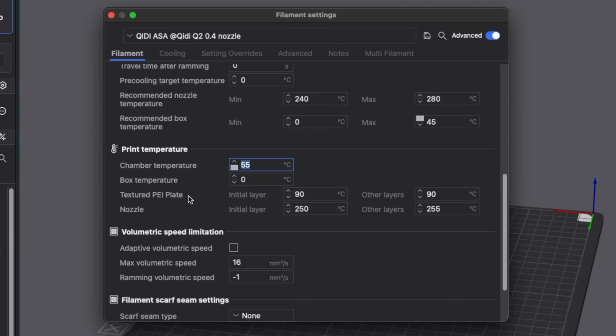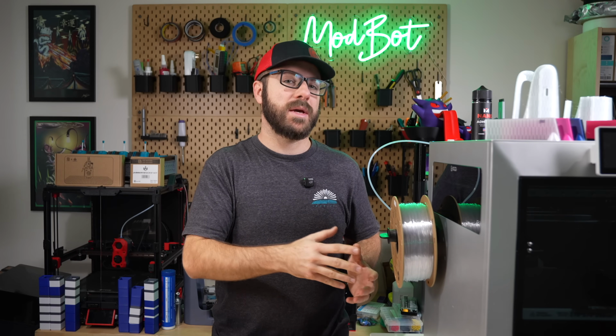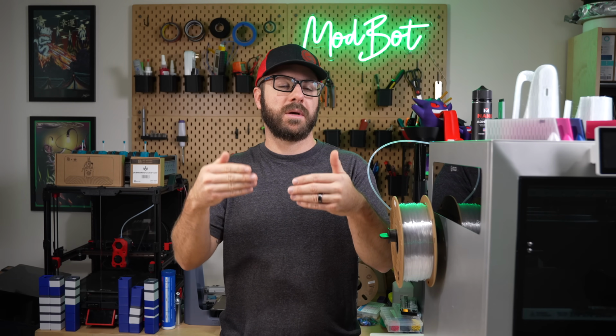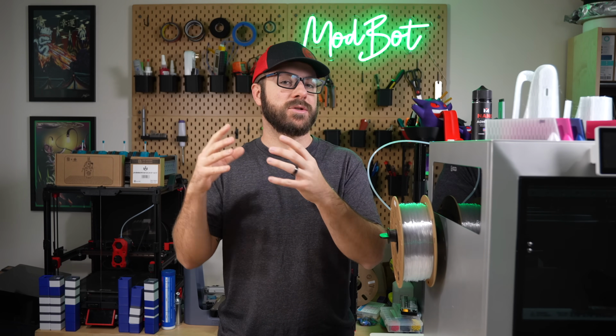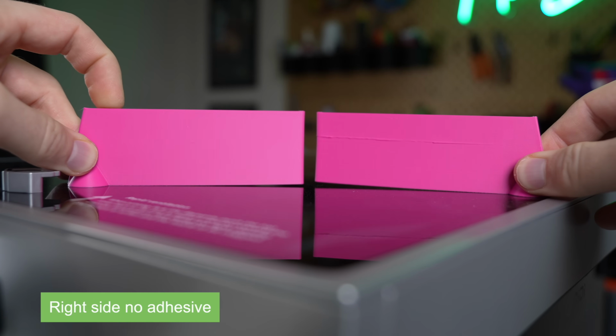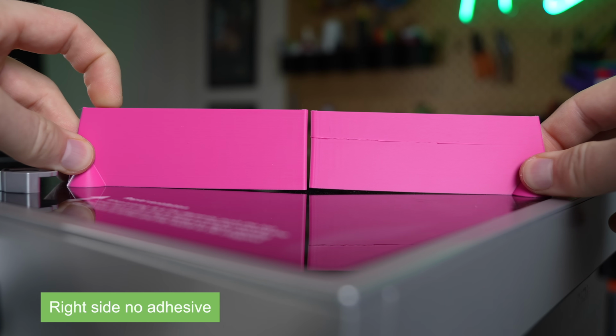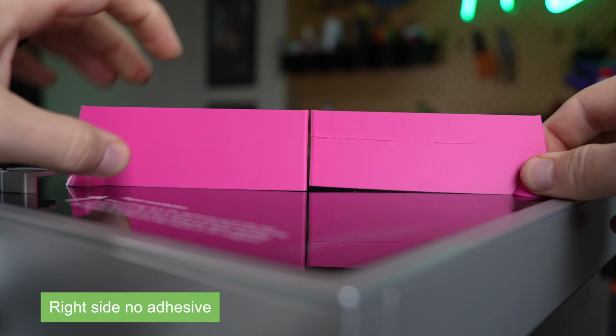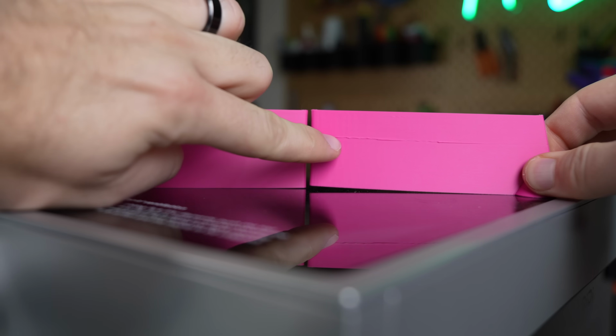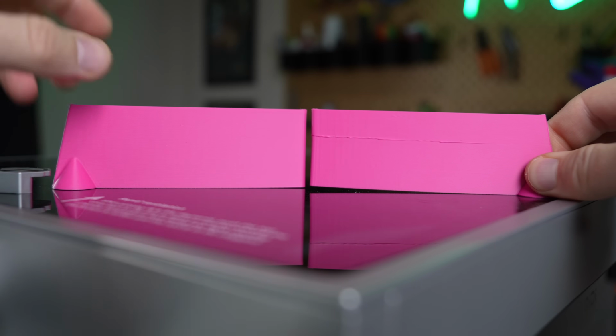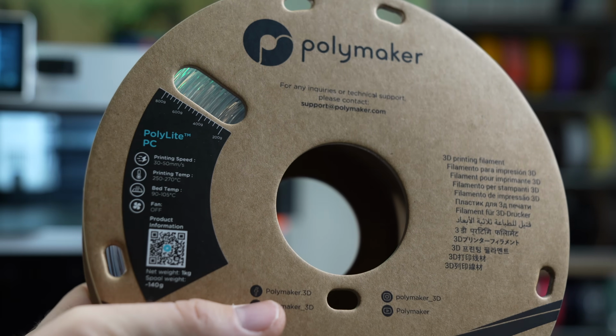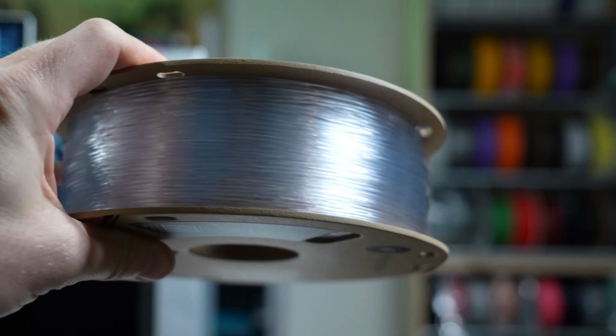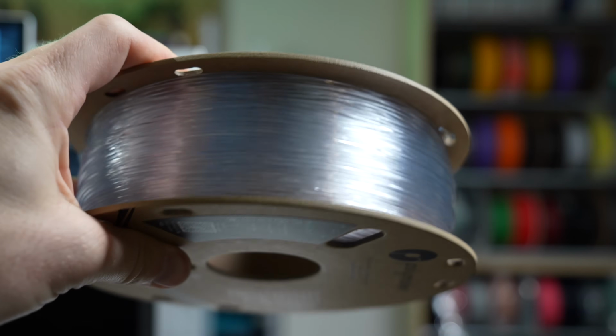For this, the slicer profile had the active heated chamber enabled, and as you'd expect, it warped less, but both parts still warped. Compared to the ABS prints, the difference between the warping on the ASA parts was much less drastic. However, the one not using adhesive definitely warped more, and you can really see this by the bulgy line that was caused by the layers underneath it curling up and just making that layer inconsistent. The last of these warp tests consisted of printing with polycarbonate, which is a material really known to warp.